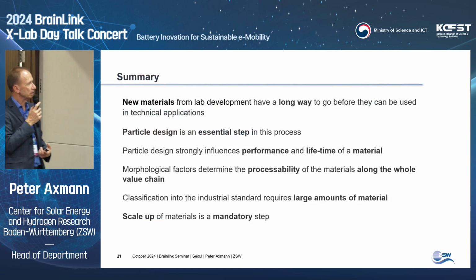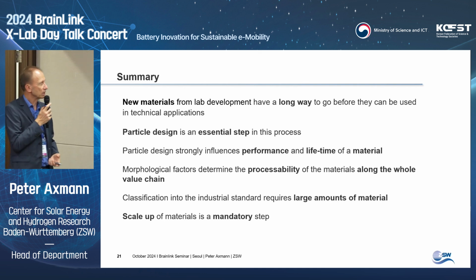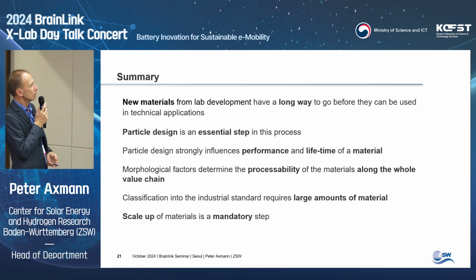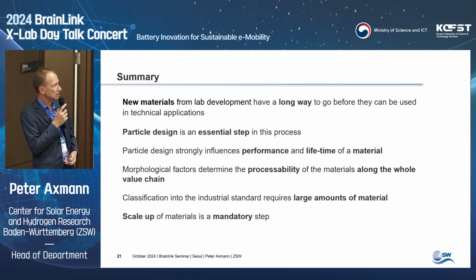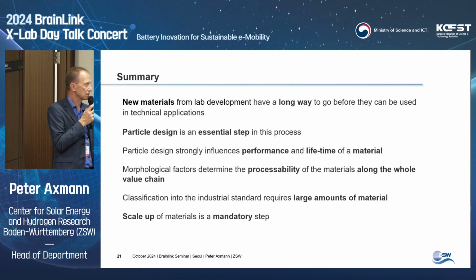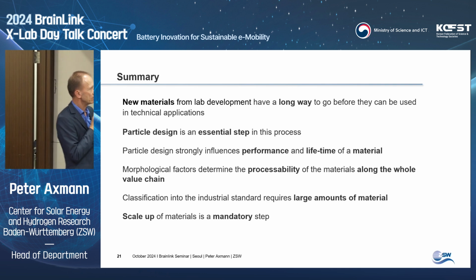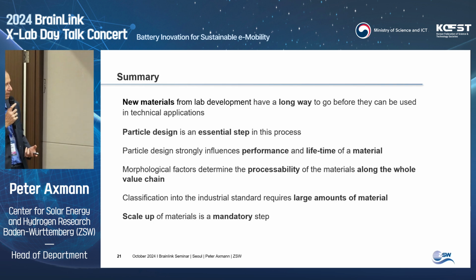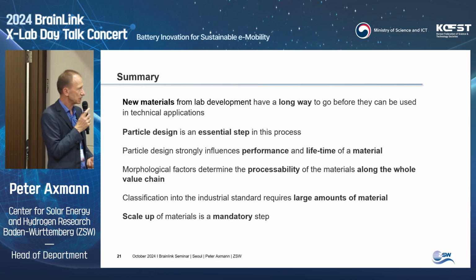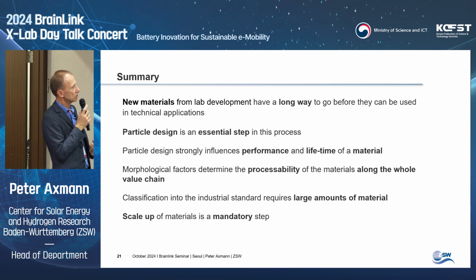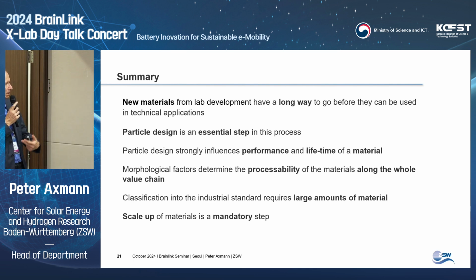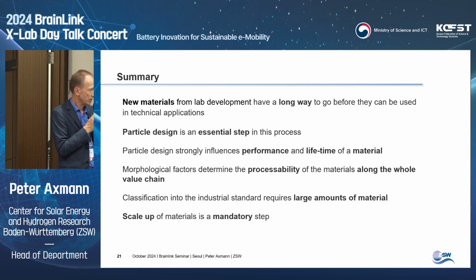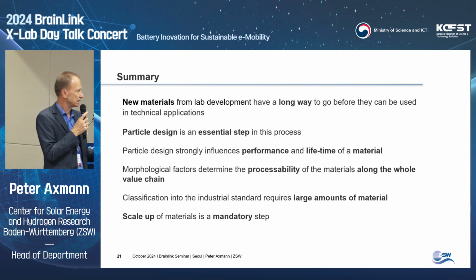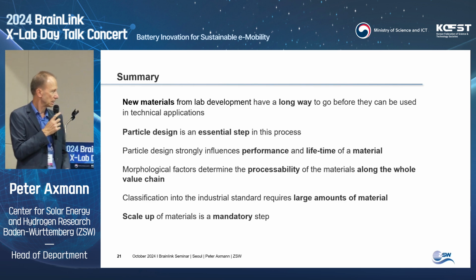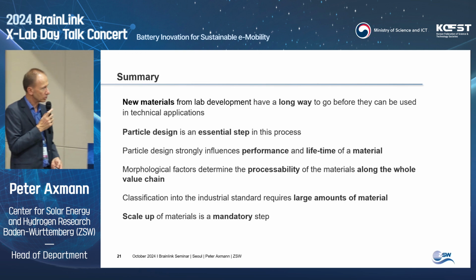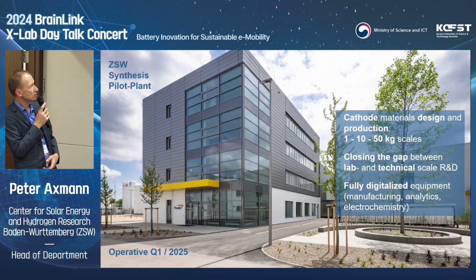If we have new materials from lab development, they have a long way to go before they can be used in technical applications. We see that particle design is an essential step in this process, and this particle design on the one hand strongly influences the performance and the lifetime of a material, but on the other hand, these morphological factors determine the processability of the materials along the whole value chain, from coating, calendering, and drying, to manufacture in the end. And if we then want to go into the classification of the material in an industrial standard cell, we need really large amounts of materials, and scale up of these materials is then a mandatory step. And this is what we are going to do very soon at ZSW.